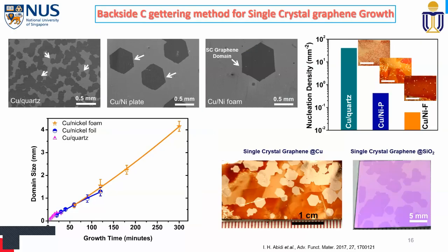But using this gettering approach, we were able to control the nucleation density. For example, on the top left corner, you see a lot of hexagons, so nucleation density was quite high. At the same time, in the same kind of area, you have only one nucleus sitting in the middle for the single crystal graphene. Using this kind of method, you can control the nucleation density, and also control the formation of unwanted bilayer patches in the graphene. So you can have a very nice single layer and also single crystal.